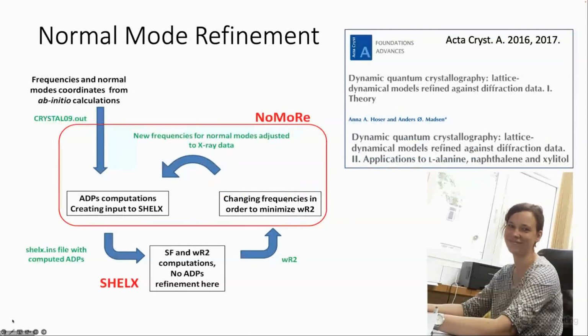This is a collaboration with Anna Hoser, and Anna and I have been working for quite a while on this together. We published back in 2016 and 17 these two papers in Acta Crystallographica A, where we show how to go about doing these refinements, starting from the displacement or normal mode coordinates and frequencies calculated with the CRYSTAL program, but it could be any periodic DFT code. We compute the ADPs, as I have just shown you, and we create input to the SHELX program, and we have used that as a tool to derive standard crystallographic refinement indicators. We are then changing the frequencies that we originally got from the ab initio calculations in order to minimize the R factor, so to optimize, so to speak, the structure with respect to the experimental diffraction data.